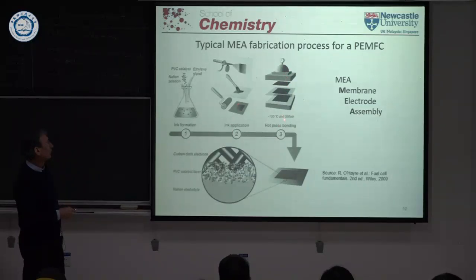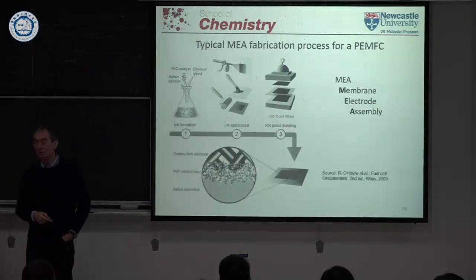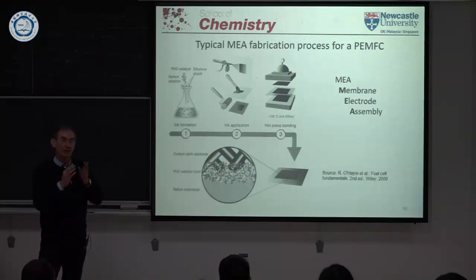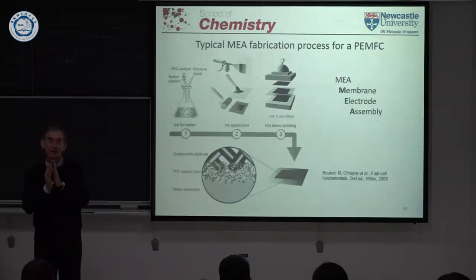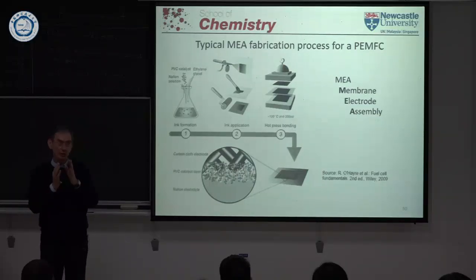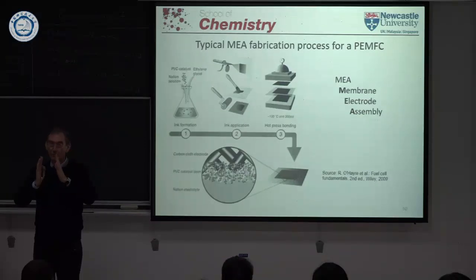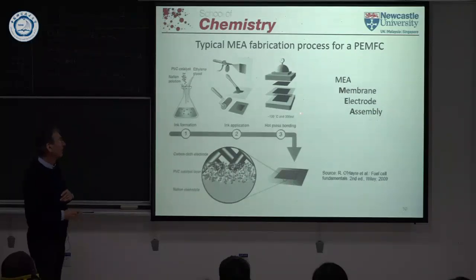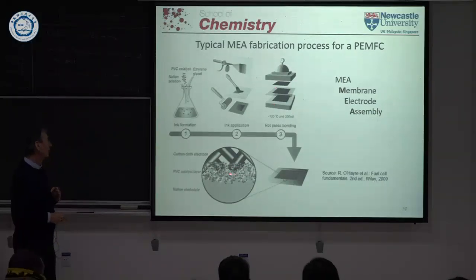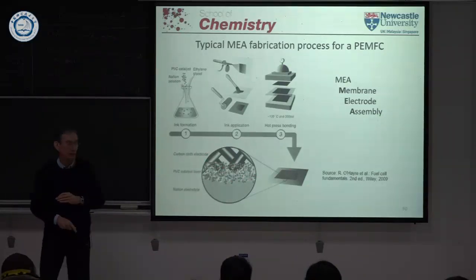And then you put actually all these layers together and have a so-called hot press, which typically is done at about 130 degrees. That is a temperature where the membrane actually, it's about the glass transition temperature of the membrane. And so the membrane becomes actually a little soft, and you make an intimate connection between these different layers and the membrane. Then this is actually what you get in the end.